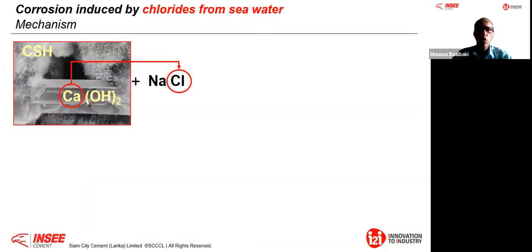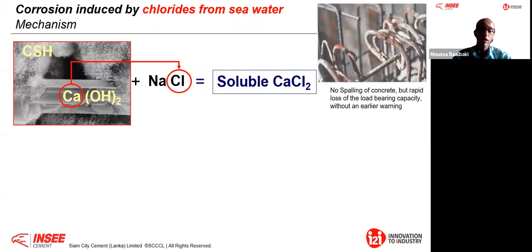Now, there is also corrosion coming from chloride in the marine environment. Here again, the chloride combines with the calcium in the Portlandite, forming calcium chloride. If you don't master and mitigate the chloride diffusion, or ingress, in your concrete, suddenly you have a pitting battery happening in your reinforcement and corrosion starts. But the danger here is what? That you don't see the rust, because the reinforcement is disappearing. It's just cutting in one place. It's not the whole steel bar that is corroded.